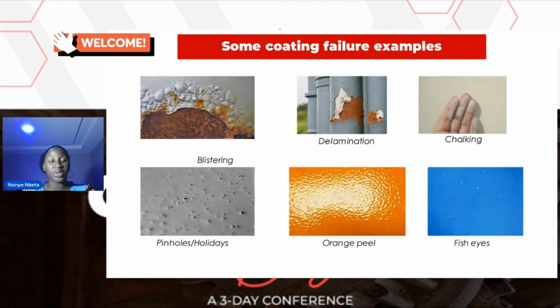So I just picked very few common ones. We see blistering, which is as a result of moisture or salt contamination. Delamination, you see rusting happening beneath a coating film. Chalking, which is mostly associated with paint coatings. Then pinholes, like we have here, orange peel as a result of poor spraying techniques, and fish eyes too. These are quite common. It's just for me to let you know that the fact that they are common does not mean they should actually be happening.